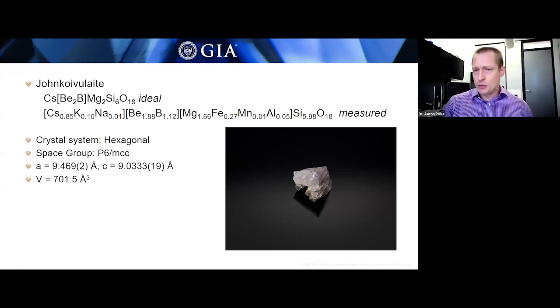And I didn't touch on it too much, but we also did single crystal X-ray diffraction on this mineral. That's a way of getting a much more accurate and precise chemical structure than you can get from the EBSD alone. But the basic results are here. So we were able to take this data, submit it again as a proposal to the IMA, and we got the mineral accepted with this name, johnkoivulaite, with this ideal chemical formula shown here.